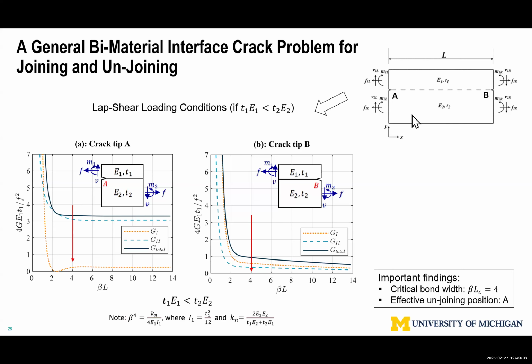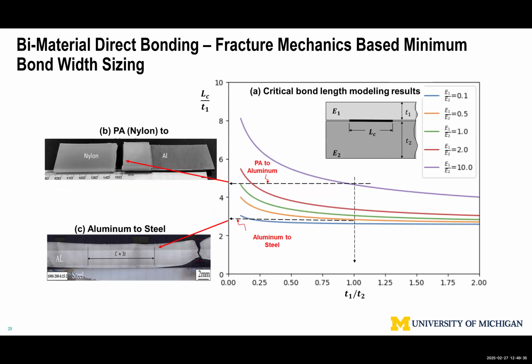Using fracture mechanics principles, we can demonstrate for a given two-material combination: I want to use this condition to produce the best structural strength under fatigue fracture loading conditions. Use this other condition, I can open it. I don't want my enemy to know it, right? So I can open it when needed, either for repair or remanufacture. So with that in mind, we've got to design the bond so effectively, so efficiently. We don't want to overbond, because later on we want to make it easier to debond. So we developed criteria for arbitrary material combinations.